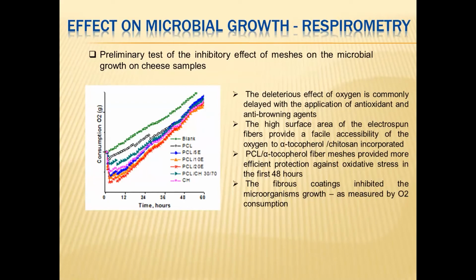In general, the deleterious effect of oxygen is delayed by application of an antioxidant or anti-browning agent. In the case of electrospun fibers, the high surface area provides a facile accessibility of the oxygen towards the active component incorporated in the fiber, in our case alpha-tocopherol and respectively chitosan. The results obtained showed that PCL fibers containing alpha-tocopherol provided a more efficient protection against oxidative stress in the first 48 hours. But generally, all the fiber meshes tested inhibited microorganism growth as measured by the oxygen consumption.